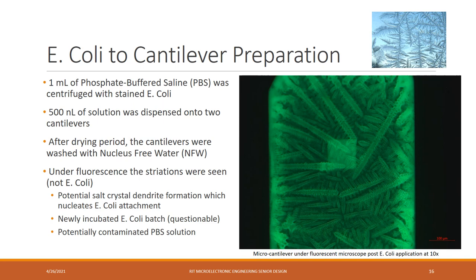One milliliter of a PBS phosphate buffered saline solution was mixed with E. coli. 500 nanoliters of this was dispensed onto two cantilevers and dried. After washing with nuclease-free water and drying again, the samples were observed under fluorescent microscopy. During this microscopy, large striations were seen that resembled crystal-like formations, similar to water crystals forming with frost. Likely these are salt crystals forming under the saline solution. Once formed, the E. coli is binding to these crystals as opposed to the silicon surface. The same procedure was followed with the addition of newly incubated E. coli. Further investigation needs to be completed to determine the cause of these crystal formations.